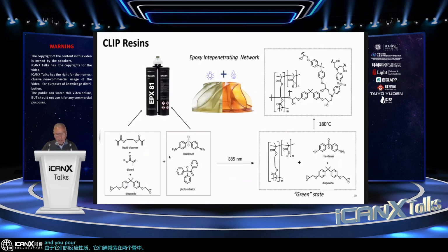And you pour that into the reservoir and you print it at 385 nanometers and you generate an object. But the light curing component might only be 20 volume% of the resin. The other 80% is the epoxy chemistry. And so you make a fairly weak, mechanically weak object, that is basically a network that contains other monomers that you can then do a solid state polymerization with to mature the properties. So it's a 2-step process using orthogonal chemistry.